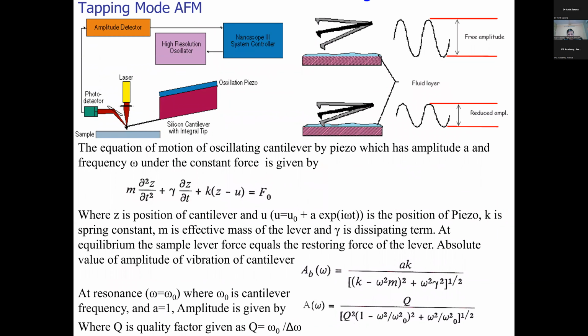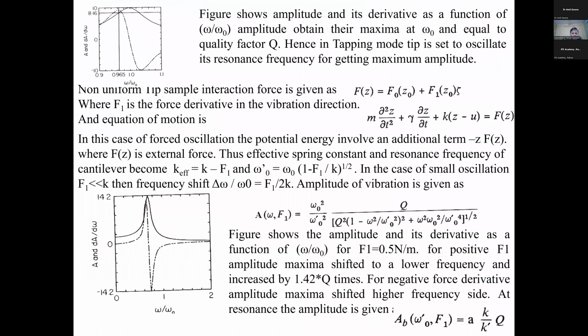Now, a bit special thing is, what do you do if there is a soft material? Like a polymer or like a biological sample, like E. coli bacteria, how to view it? Very difficult for AFM. So they invented a beautiful technique. You just take another piezoelectric. This is a piezoelectric silicon cantilever. They keep one more piezo here and apply an electric field, a 4th piezo. X, Y, Z are already here, and this is one more extra for the cantilever. This will give an oscillating electric field. The tip also will oscillate up and down. You go once away from the sample, then come nearer to the sample. When you come nearer, only then you have force. Otherwise, you don't apply constant force. Therefore, soft samples can be seen here. It's a very big deal.